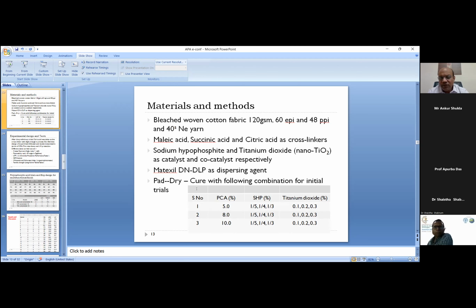So now coming to the actual process. In the materials and methods, bleached cotton fabric was taken. In fact, the initial trials were taken with maleic acid, succinic acid, and citric acid. All three were first used. And sodium hypophosphite and titanium dioxide were also applied. Titanium dioxide normally has a problem of uniform dispersion, so Matexil DN-DLP, this is from Croda, was used as a dispersing agent.